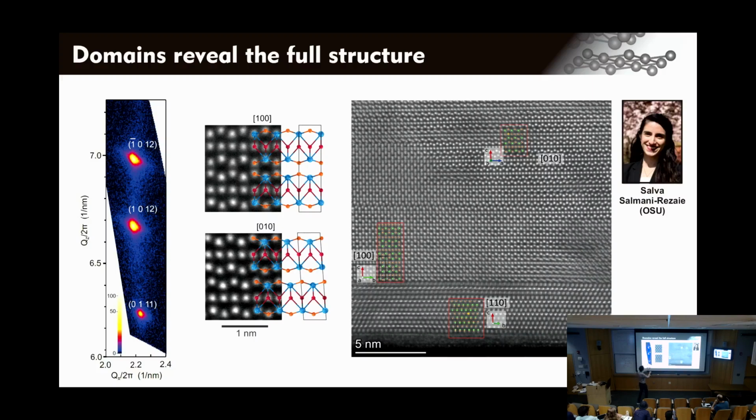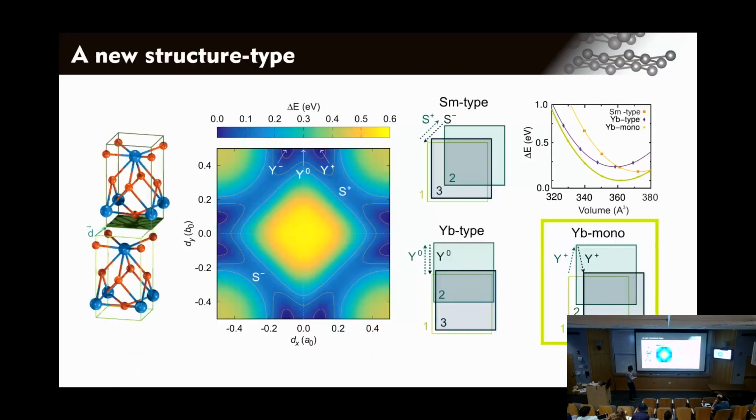If you really zoom in, you can see that one axis looks rectangular, kind of orthorhombic, whereas along the 90-degree axis, it has this tilt associated with it. This was associated with a monoclinic phase. The bulk is orthorhombic globally, so it was very surprising to us to see a monoclinic phase. And this splitting here corresponds to the monoclinic angle.